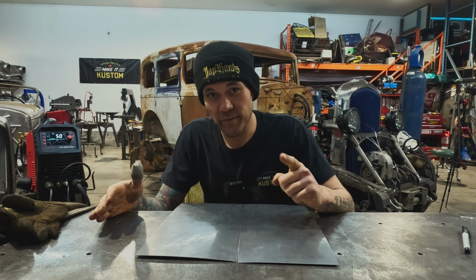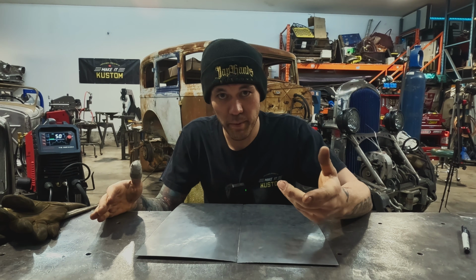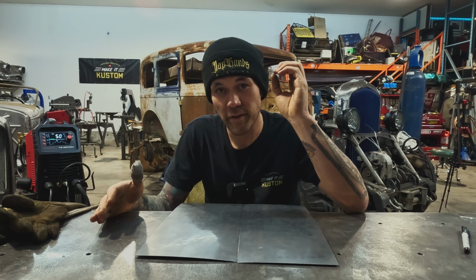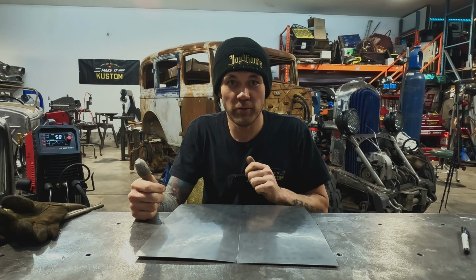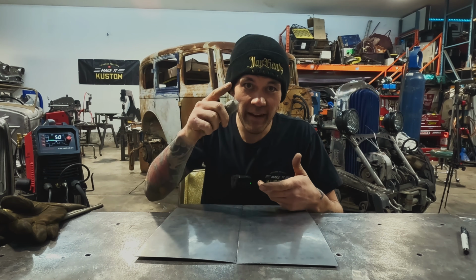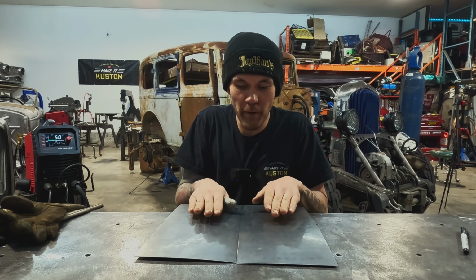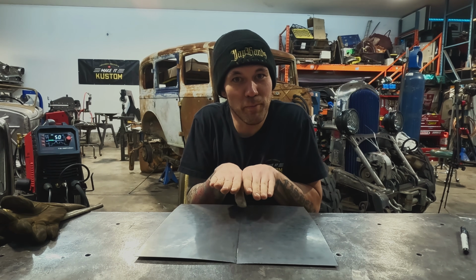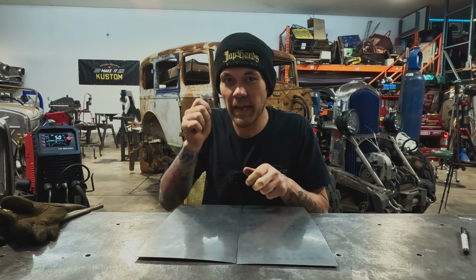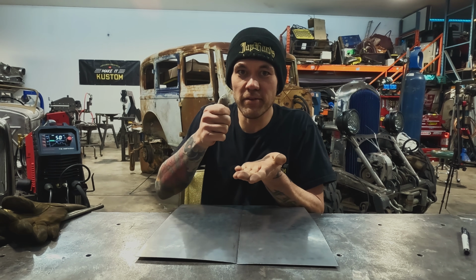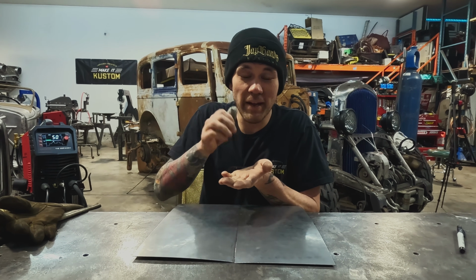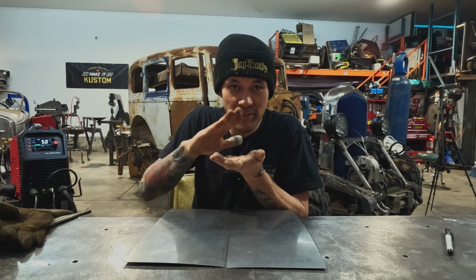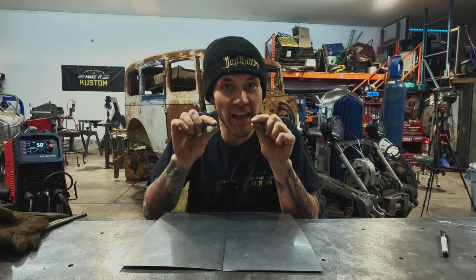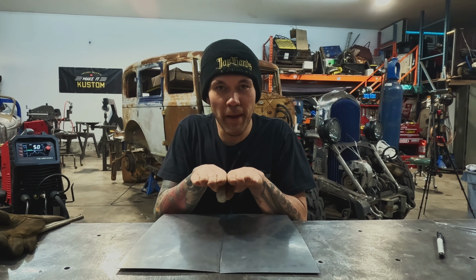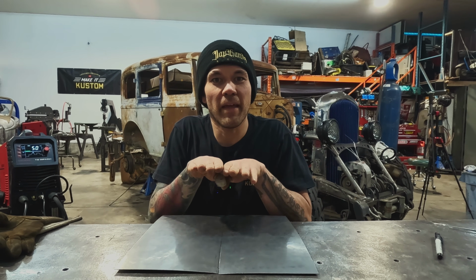During that process of tacking, something else is going to happen. You're going to experience tack shrinkage. So what you need to do is tack, and if it tightens up to the point where your panels are pressing together too much or they want to overlap, you have to take a hammer and a dolly underneath your tack, give it a whack, two whacks, just hit the tack enough to stretch it out a little bit to allow your panel to open back up and relax.